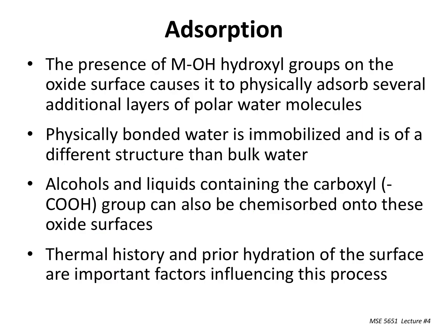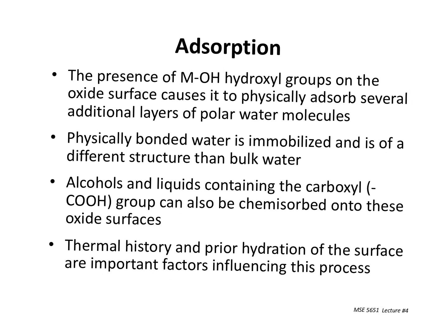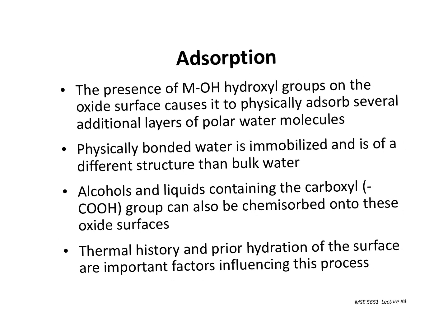Last slide. So the presence of the metal hydroxyl groups on the oxide surfaces causes it to physically adsorb several additional layers of polar water molecules, all right? And as I mentioned earlier, the physically bonded water is immobilized and is of a different structure than bulk water. It can be higher density than bulk water, and then above that surface it can be lower density than bulk water. And because water is present, other things in the environment like water, all right?